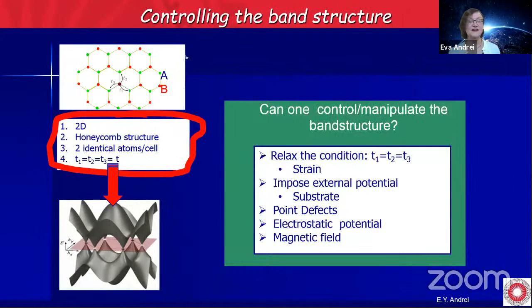So now this gives us some idea of how we can control the band structure in graphene. And the same can be done with other two-dimensional materials. One way of doing that is to relax the condition that the three hopping parameters are the same. You can do that by applying strain, stretching the layer. Another way is to impose an external potential, like putting it on a substrate.